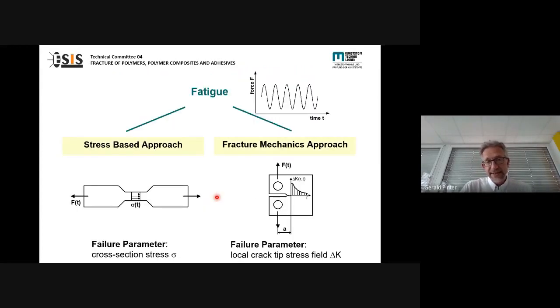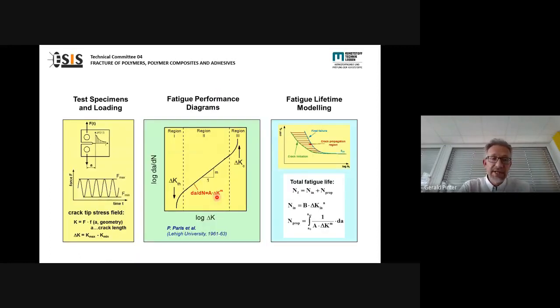So that's it. Only finally now to the fracture mechanics approach. Andy Bruno will go on in the next presentation looking at composites, and you also heard about it during the day. So we have fatigue loads. And the most important aspect going into fracture mechanics is that we measure the crack growth as a function of the cycle number. We have the crack growth rate as a function of the K value or the G value. What you typically see in a double logarithmic diagram is the so-called Paris plots. With these Paris plots, you can do material comparison, but on the other hand, it is also possible to really do lifetime calculations.